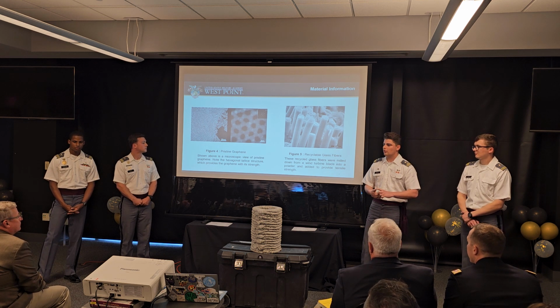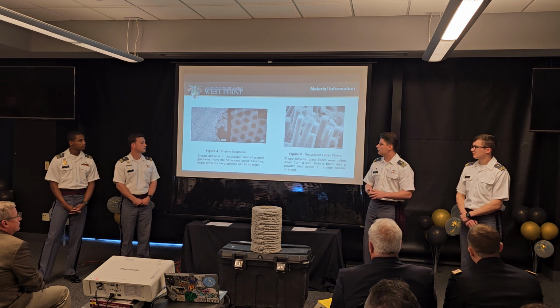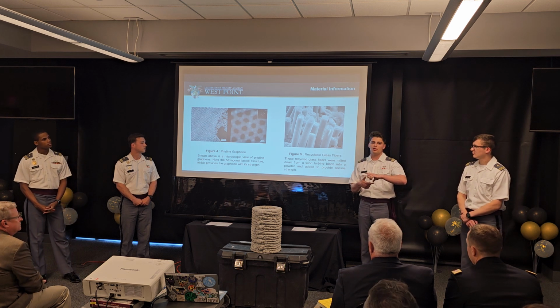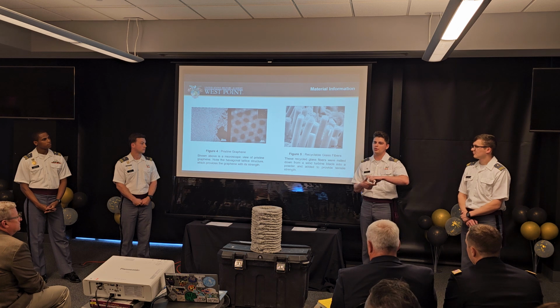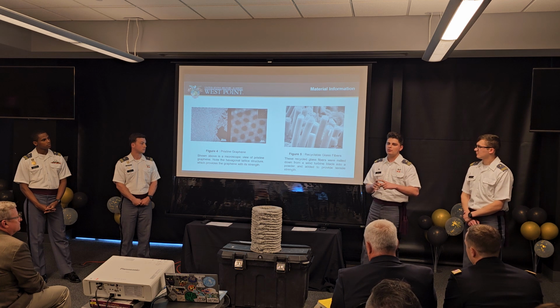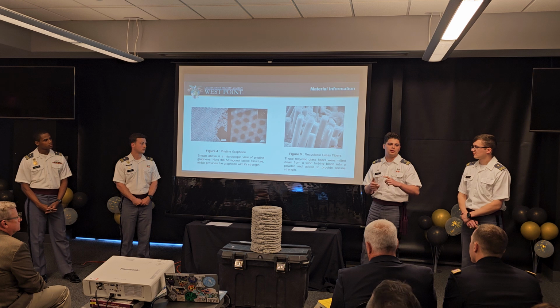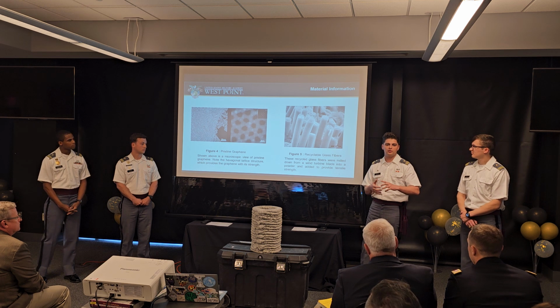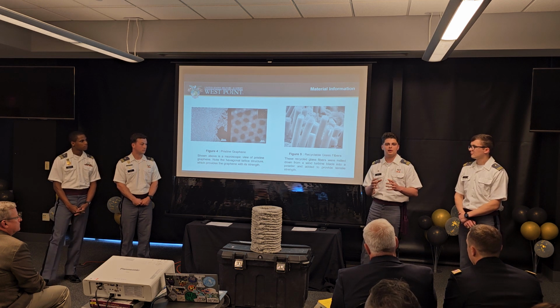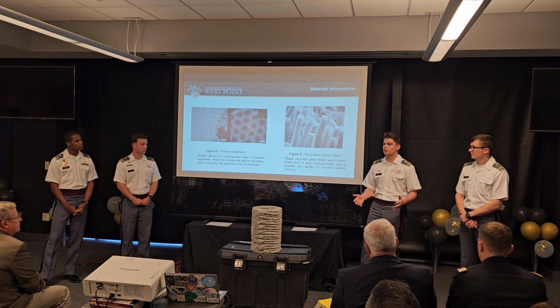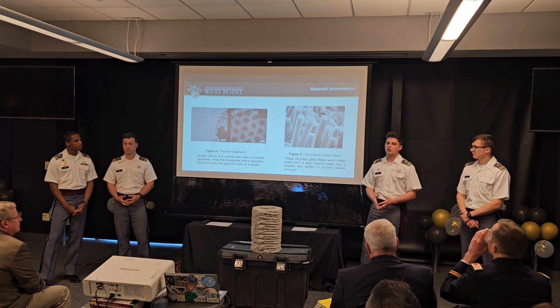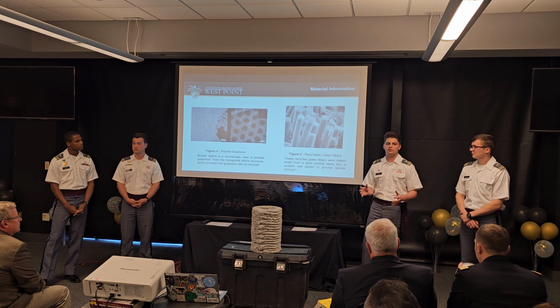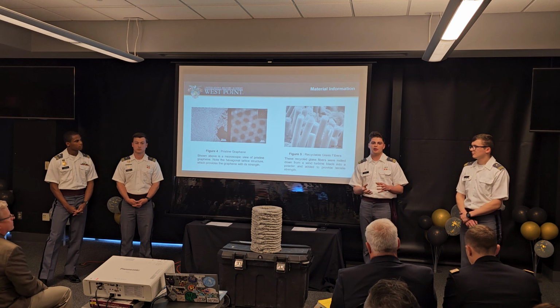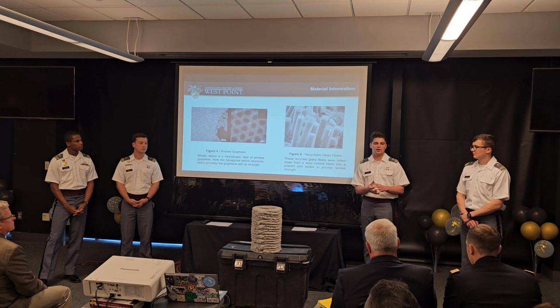This is a hydrophobic substance, as Nick mentioned earlier, and it's formed in a hexagonal lattice based off of the molecular compound of carbon. Because of this compound, it's very, very strong. It doesn't have a lot of loose molecular parts, and so it's very, very tough. So when used in an admixture, like concrete, it provides a lot of compressive strength. It essentially fills in the void spaces that the concrete's gonna have due to difference in aggregate sizes, wrapping around those particles and making it a more unified object.